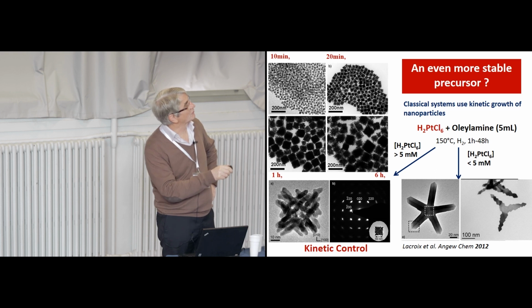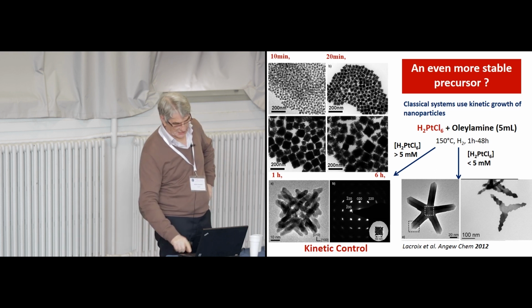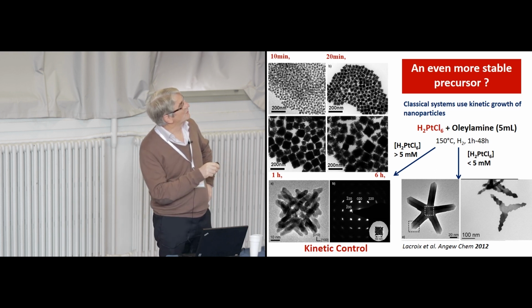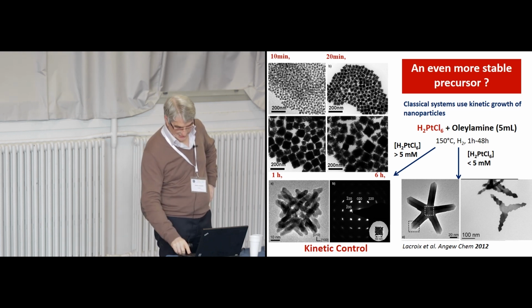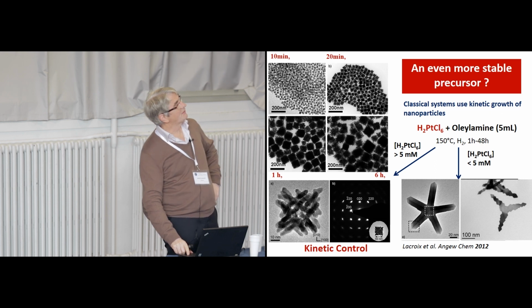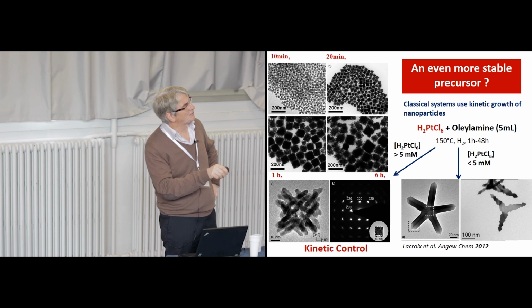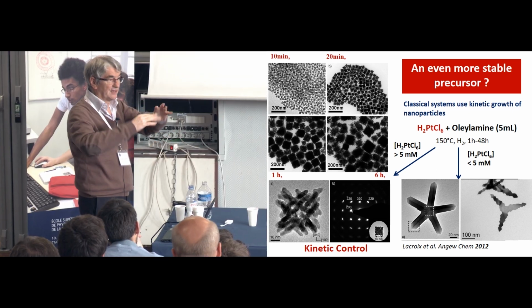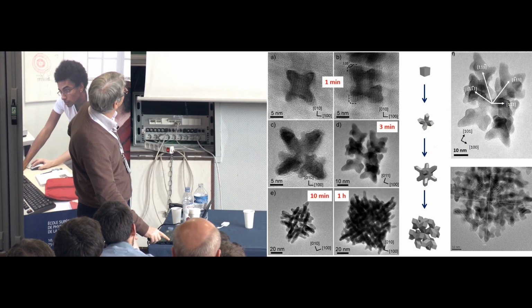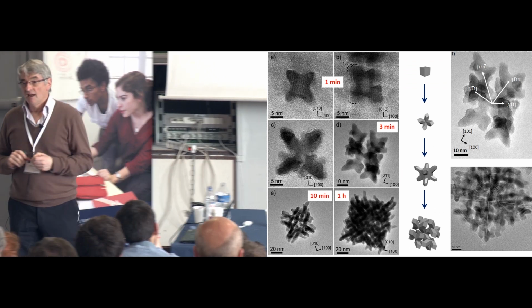And we could follow the growth. Very nice, here we could see that we have some decahedra and icosahedra seeds. This is tomography, which shows why we can have a five-fold symmetry, because it's not flat in the center.